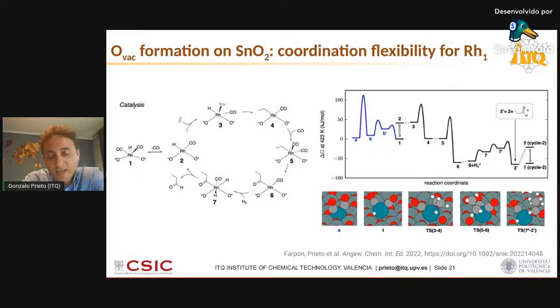The highest energy barrier for this mechanism is indeed in step 3 to 4, that's the insertion of ethylene into the rhodium hydride bond, and is subject to just a 90 kilojoules per mole free energy barrier, as I'm showing on the diagram on the right-hand side. And that actually explains why these types of centers could be so active under mild reaction conditions for ethylene hydroformylation.